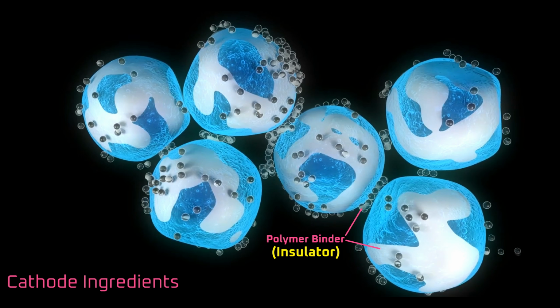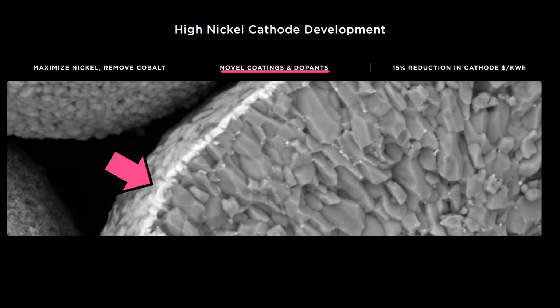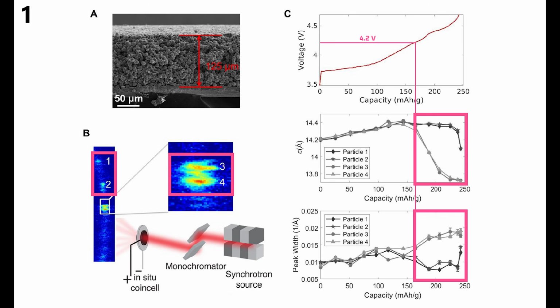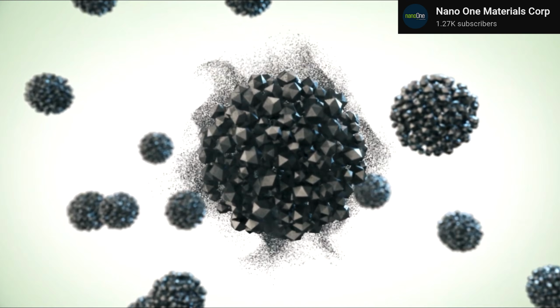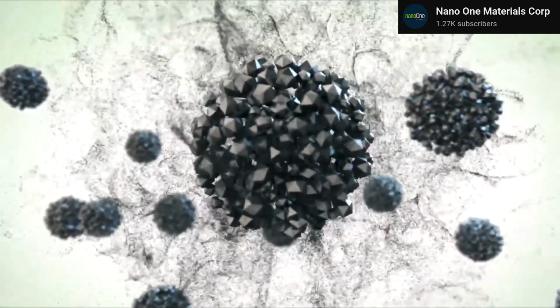That is, the poor electronic network created by the wet process is the core problem and weakest link in the electrochemical chain. So it's no wonder there's been limited success at solving high voltage degradation through improved electrolytes and better cathode designs. While those solutions might improve durability up to, for example, 4.5 volts, the reality is that in a cathode running at 4.5 volts, some of the individual cathode particles might actually be spiking up to 4.8 volts or more, leading to rapid degradation despite the improved durability.